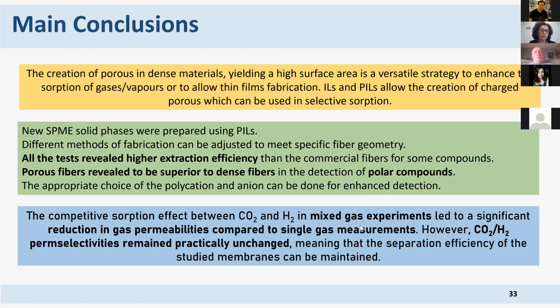So I hope that I could show you that the creation of pores in dense materials yielding high surface area is a very versatile strategy that can be used not only in analytical applications, but also for the fabrication of thin films to be used in membranes. In the SPME, all the tests that we've done reveal that these fibers with pores are much more efficient than those that are dense fibers. On the other hand, we can also selectively extract polar compounds due to the porosity, the porosity being charged.